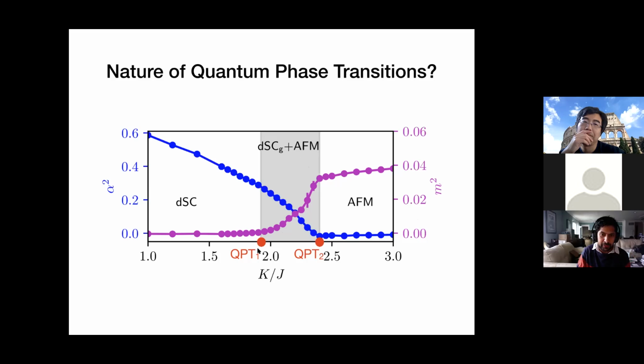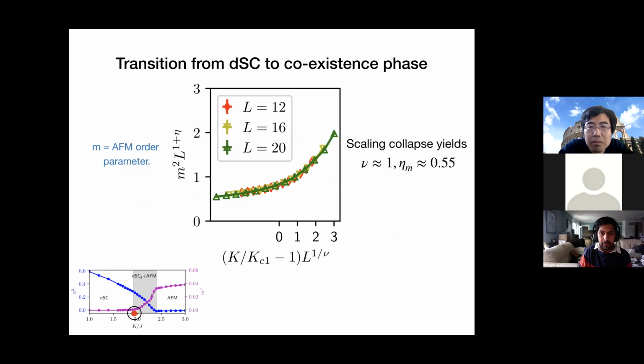This one is more interesting because there are gapless fermions at this transition. We are going from gapless quasiparticles to gapped quasiparticles, and you're also breaking spin rotation symmetry. So this is a somewhat more interesting transition, so let's focus on that. You can look at the anomalous dimensions and do some scaling collapse. Of course, these are small systems, so don't take these numbers too seriously; 0.55 may become 0.6. It's not as accurate as some large scale QMC simulation. These are small systems up to 20 sites, but at least we get some scaling collapse, and I will come to these numbers in a minute.